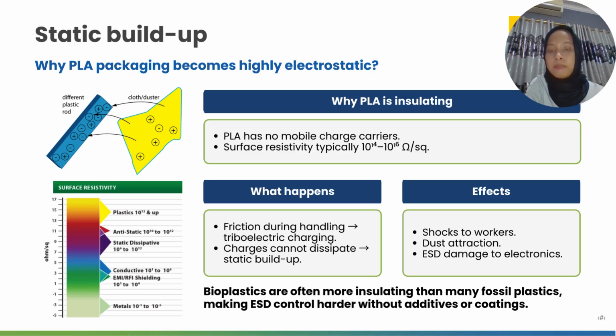Next is static build-up. The reason why PLA packaging becomes highly electrostatic is that PLA has no mobile charge carriers and surface resistivity is typically 10^14 to 10^16 ohm per square. And what happens? Friction during handling leads to triboelectric charging, and the charge cannot dissipate, leading to static buildup. The effect is shocks to workers, dust attraction, and ESD damage to electronics. And bioplastics are often more insulating than many fossil plastics, making ESD control harder without additive or coating.